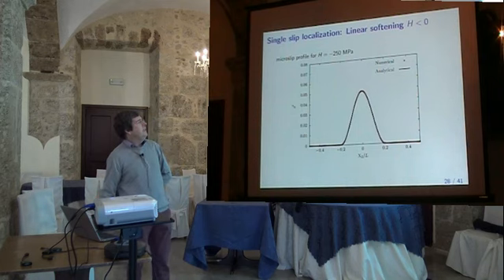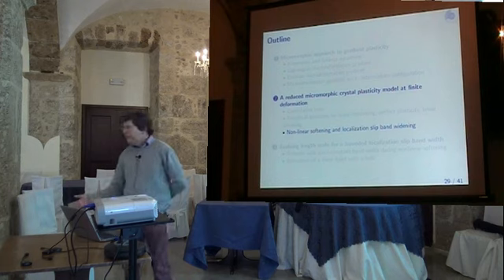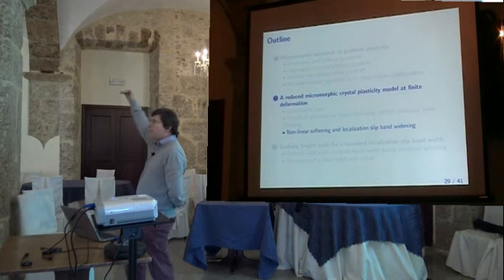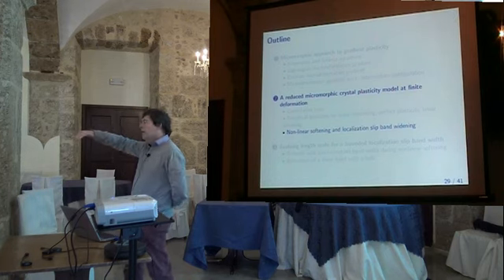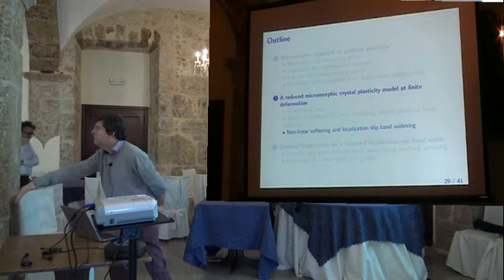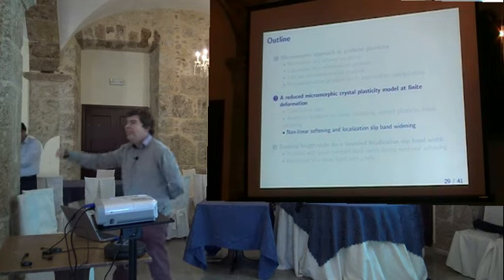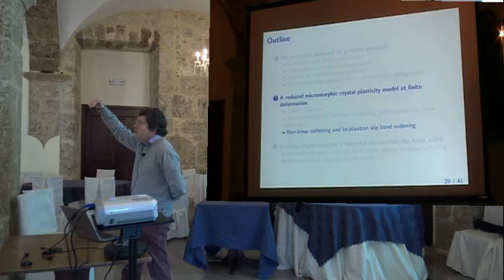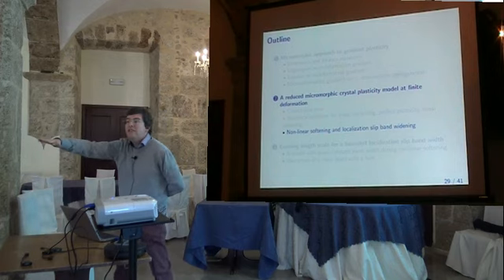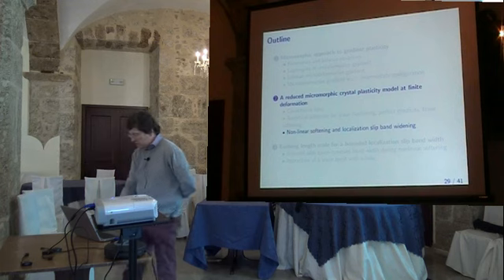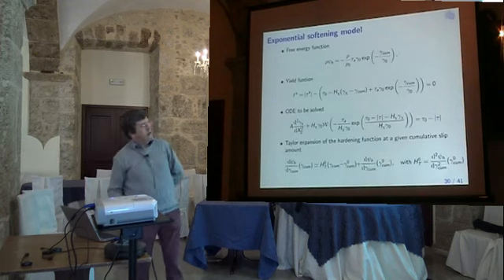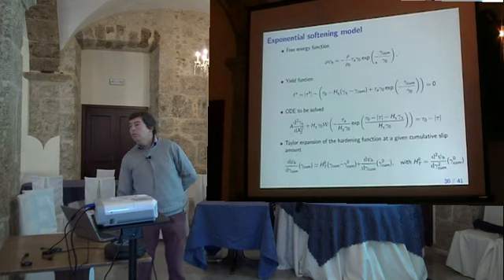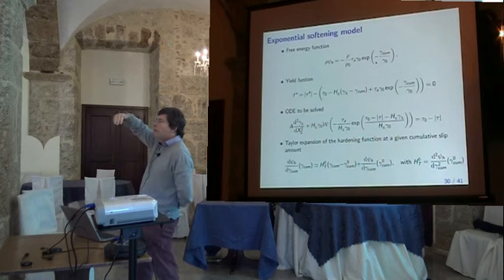Okay, and the problem is if you do large strains, if you have linear softening, after a bit of strain you will have negative stress, so it's not so nice. So at some point, the negative hardening has to stop. You have to find some limit stress or something. So this is what we are doing here. We consider some exponential function. So we take an exponential decrease.